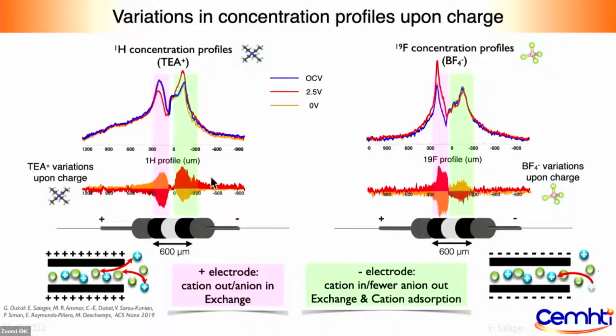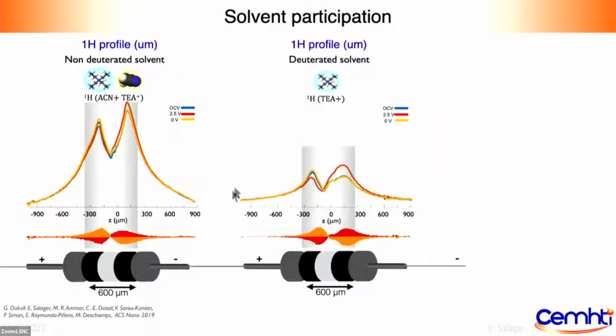And then we confirmed this by discharging the supercap. And this time we do the difference in orange between the fully discharged supercap and the fully charged supercap. And you can see that this is quite reversible. And this is one of the things that is a characteristic of supercaps. We also checked what was happening with the solvent. So I forgot to tell you, but all of this was made with a deuterated solvent so that the protons from the solvent wouldn't disturb our subtractions.